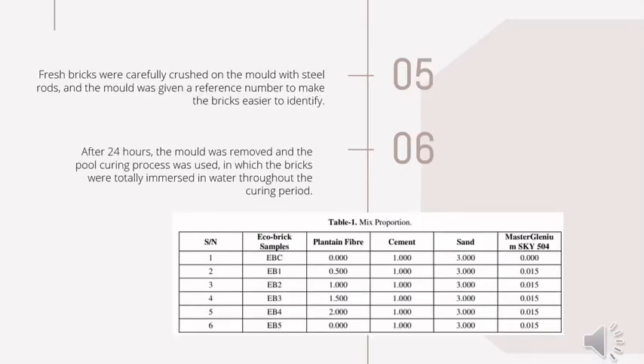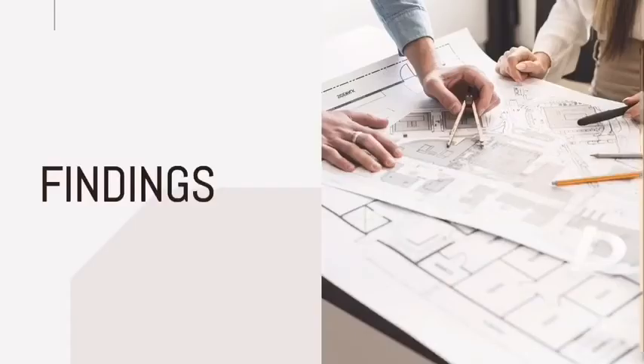Last but not least, first the bricks were carefully cast in the mold with steel rods, and the mold was given a reference number to make the bricks easier to identify. And lastly, after 24 hours, the mold was removed and the pool curing process was used, in which the bricks were totally immersed in water throughout the curing period. And this is Table 1, which is the mix proportion.